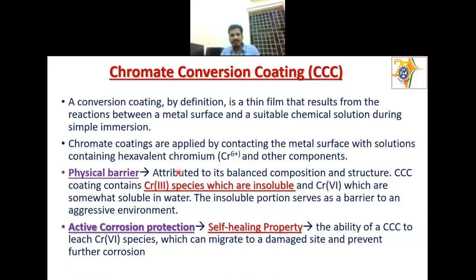And all this smartness of the coating, the use of different kinds of material, started from the chromate conversion coating. For the aerospace industry, aluminum is the material they use because weight is more important in aerospace. You can't use steel there. So aluminum, we know, has an aluminum oxide film, but it very easily undergoes corrosion in alkaline environments and environments containing chloride ions. So it undergoes pitting corrosion, localized corrosion, and filiform corrosion. So it's a big problem.